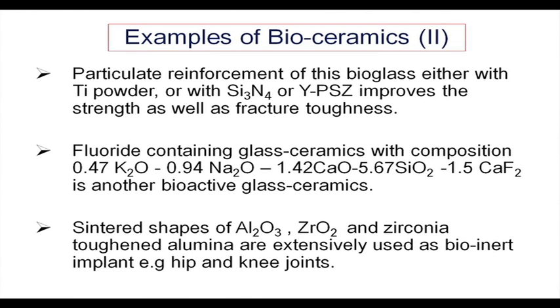So, there have been attempts to improve the mechanical property by these techniques, like particulate reinforcement with titanium powder. Titanium is another biocompatible material which has been extensively used for different kinds of bone replacement or bone repair. Wherever there is a fracture, titanium is one of the materials always used, but that is a metal. So to improve the mechanical properties of the bioglass, one can use compatible metals like titanium powder, or ceramics like silicon nitride and yttria doped partially stabilized zirconia. YPSZ, yttria doped partially stabilized zirconia, improves the strength as well as fracture toughness.